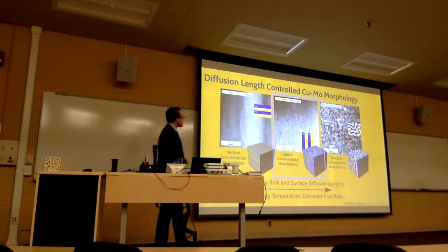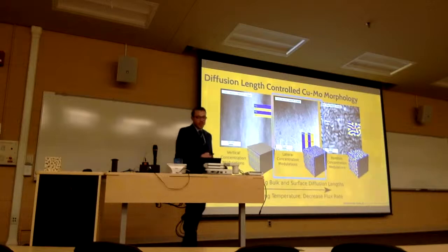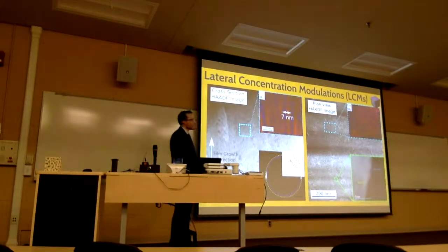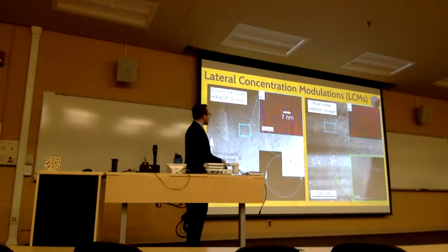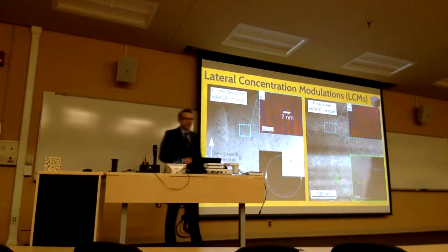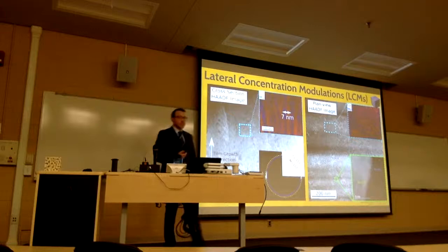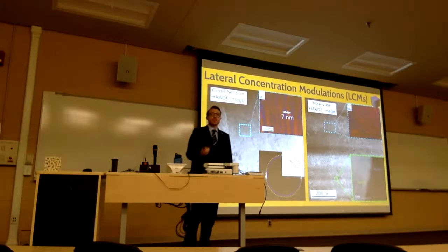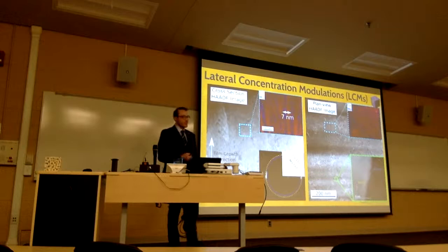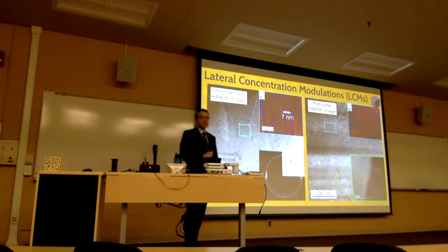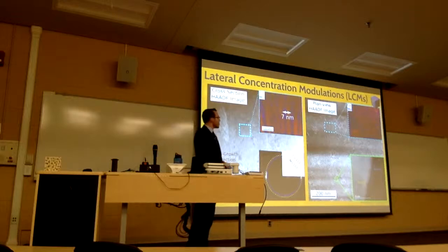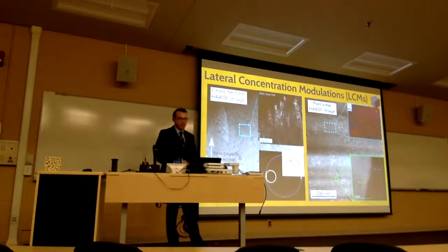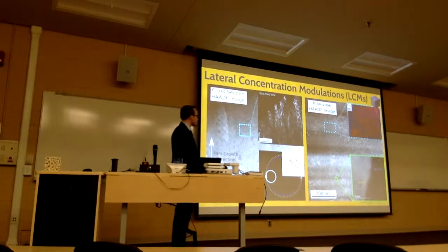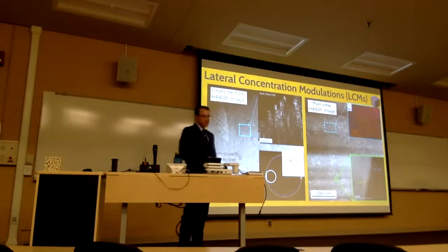At slightly higher temperature, we actually change the direction of phase separation 90 degrees into lateral concentration modulations of copper and molybdenum. You can see that here in the chemical imaging in an approximate length scale of 7 nanometers. If we take a look at the crystallography of the sample, what we see is actually the two equilibrium crystal structures for both of the constituents, both FCC copper and BCC moly in this film, when we look at the film top down. We can actually pick out frequencies in that crystallography measurement, and see that this film is highly textured when we pick out one of those peaks and measure the sample at dark field